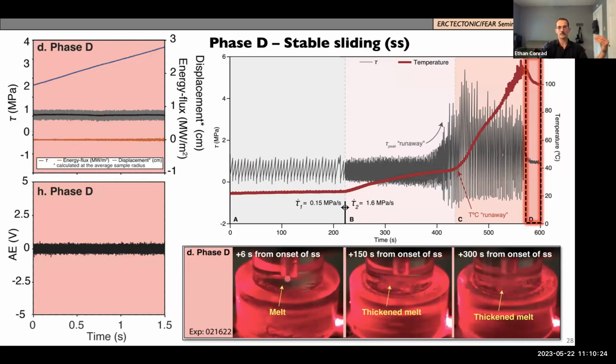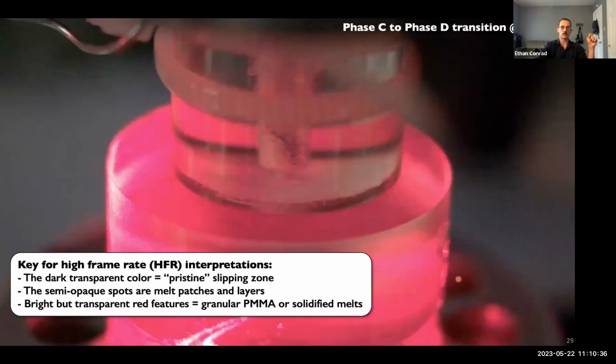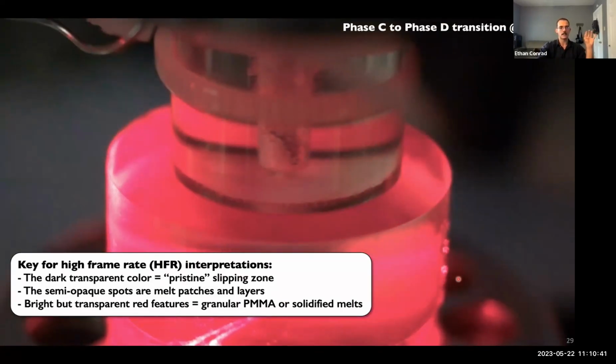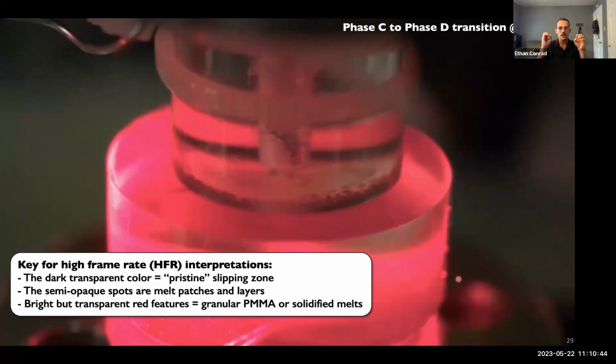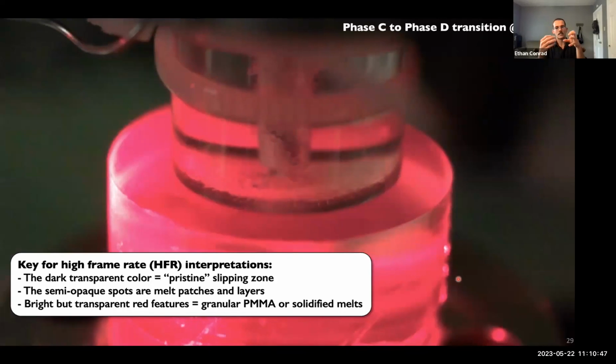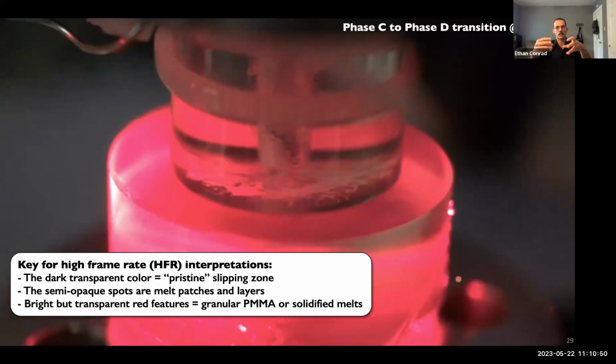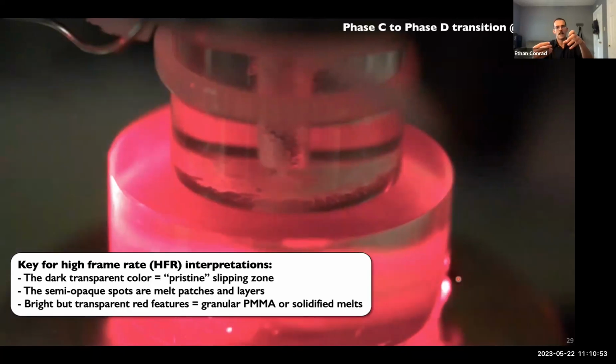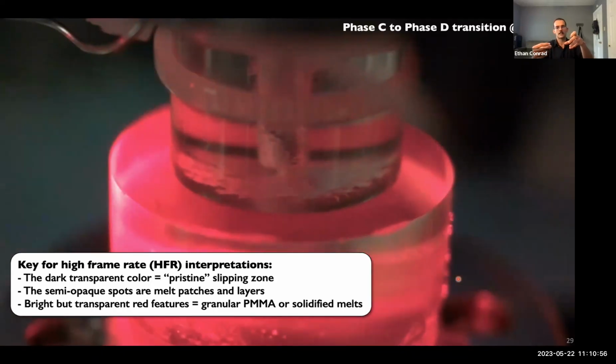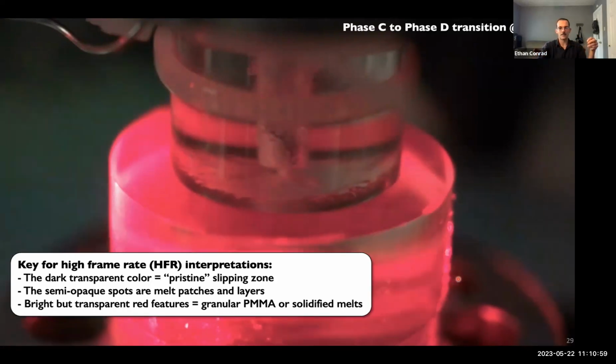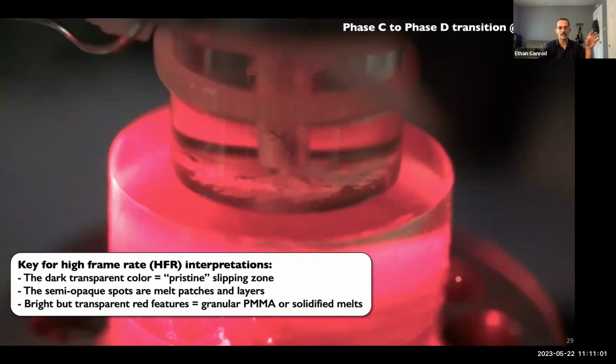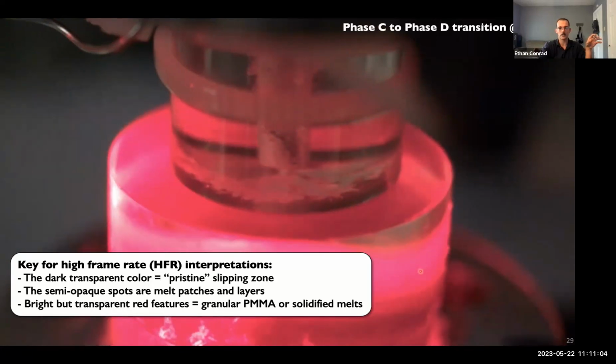We see shortly after the onset of stick slip, the formation of this melt patch. It starts to thicken and thicken more, forming this brighter red color as the experiment goes forward. And then here's looking at this transition in itself. So here's just the key for the interpretation. So we have the last event. We see the melt patch changing and fluctuating. We see another smaller event, and then it starts to slide. And so there we have it, just sliding, and the melt is going to continue growing from there.